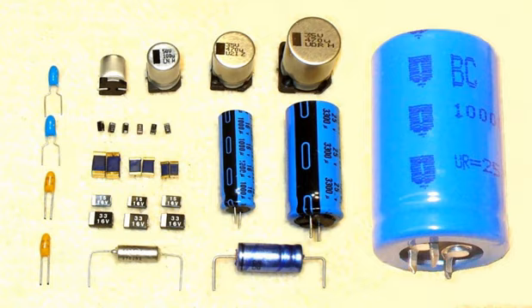If a lifetime specification of an electrolytic capacitor is, for example, 2000 H, 105 degrees Celsius, the capacitor's lifetime at 45 degrees Celsius can be calculated as 128,000 hours. That is roughly 15 years by using the 10 degrees rule.